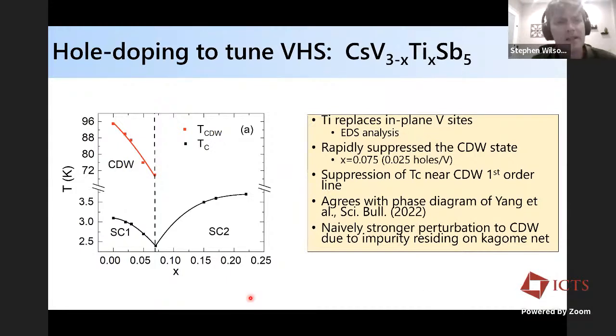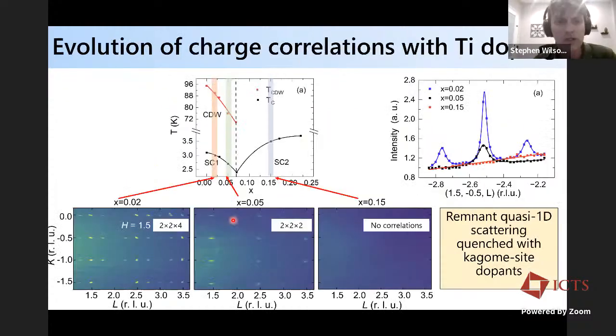So what we can also do is, instead of doing tin on the antimony site, you can do titanium on the vanadium site. And this is the phase diagram you get. And this is consistent with earlier phase diagrams that have been published. So basically, you don't get two explicit domes. You get a suppression and then a recovery once you exit the charge density wave phase. You still get this first order phase boundary between the two maxima in superconductivity. And when you look at the charge correlations across this phase diagram, what you see